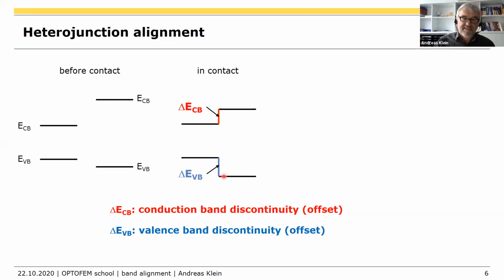So if you take, for example, gallium arsenide and aluminum arsenide, you will get in principle a unique alignment with a fixed valence band and conduction band discontinuity. Now that's again without Fermi level, but the Fermi level is not important. That means the doping of the bulk of the materials is not relevant for this alignment.